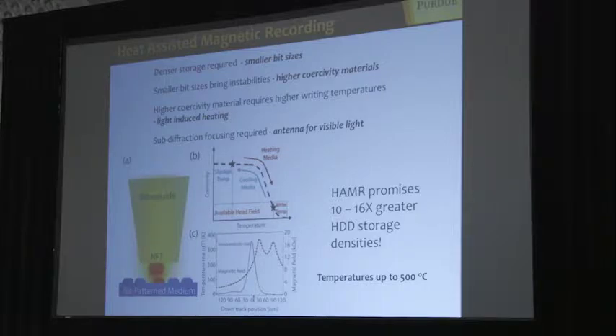So what was suggested long ago is so-called heat-assisted magnetic recording. Basically, if you heat up locally just one particular magnetic grain, then the coercivity drops, and even with a small magnetic field, you could flip it and record your bit of information. Then you cool it down, and you keep that bit of information. The way to locally heat up is to bring in this near field transducer. Basically, it's a nano antenna. You irradiate it with light, and you locally heat it up. And it could be, let's say, 20, 30 nanometer size of the bit.